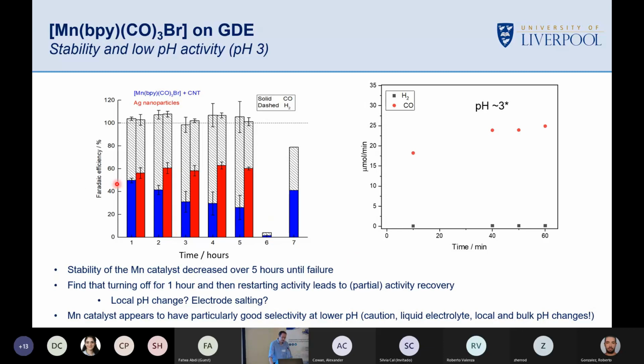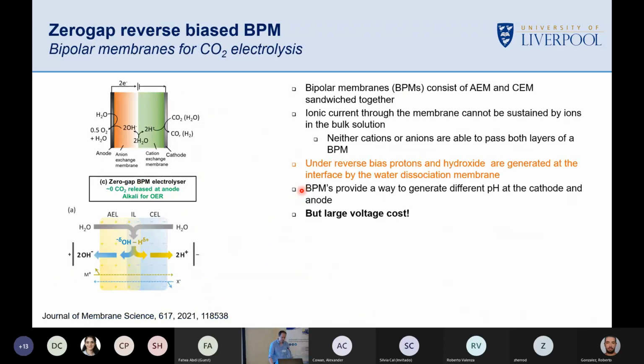Downsides, the manganese catalyst degrades over time. So after 5 hours, it seems to catastrophically fail. We switch it off and it comes back. And we think that we understand that now. We think it might actually be the local pH changes and we're going too high. So that's an interesting point. The silver you can see is much more stable. So it's an interesting species, but it's not perfect. But let's see what happens now if we put it in an acid CO2 electrolyzer.